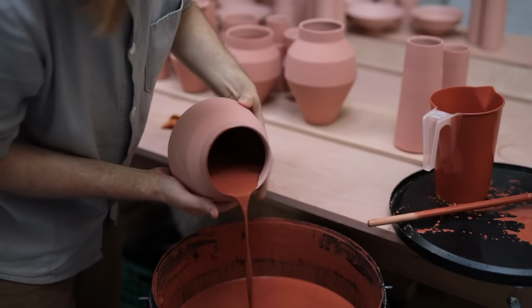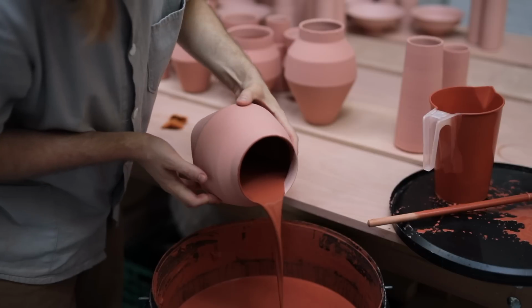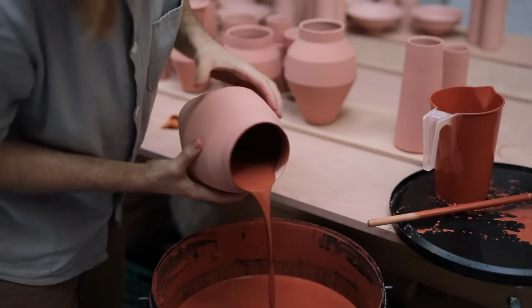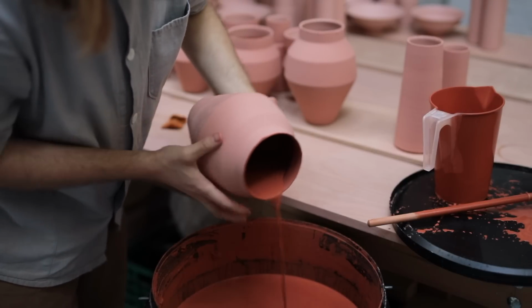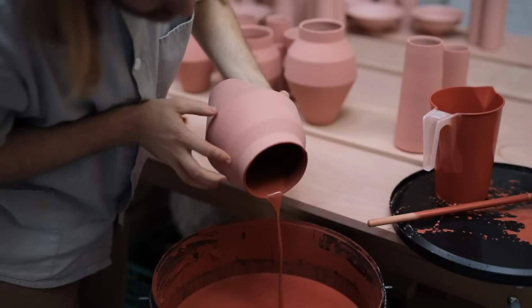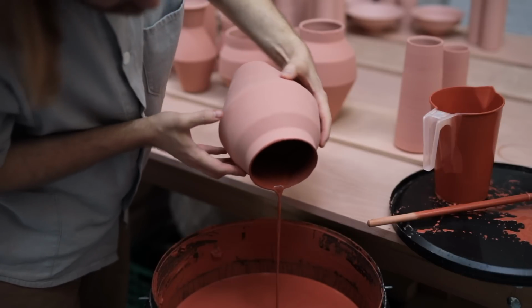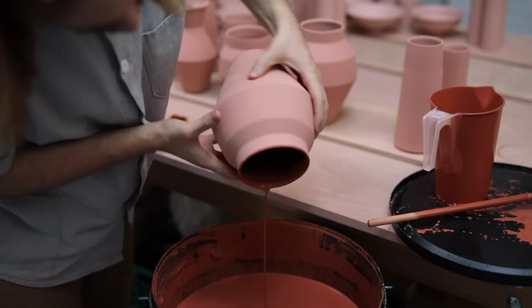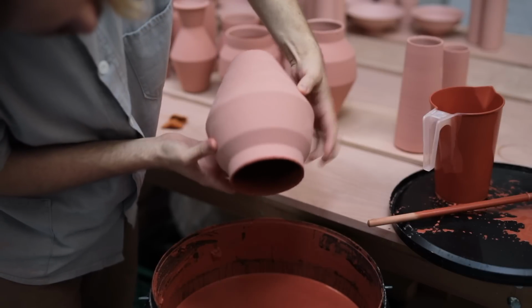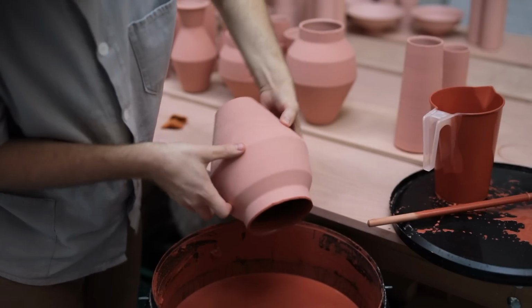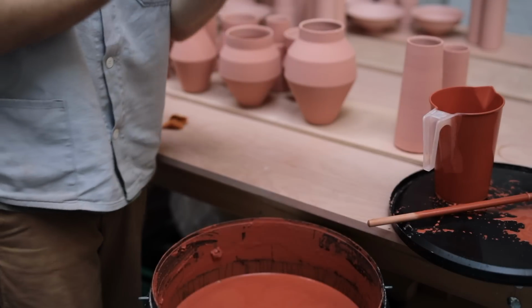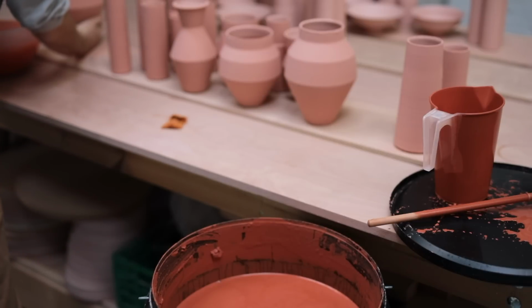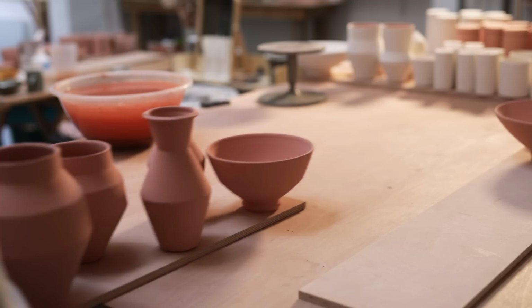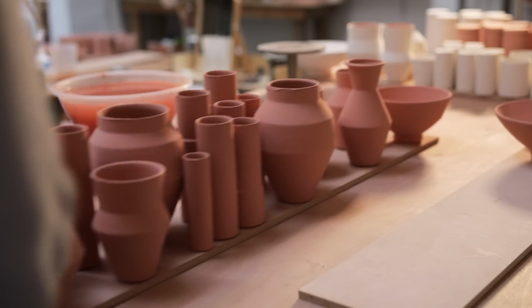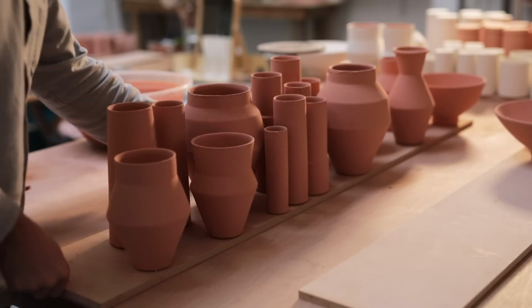And to quickly explain why I do the outside first, my glaze dries in quite a delicate layer, and if I coated the inside first and let it dry, and then gripped it from the inside to push it underneath the glaze to coat the outside, I'm pretty sure the amount of pressure I'd need to use to push the pot underneath could be enough to damage the glazed surface inside, whereas I feel it's safer to handle the outside of the glazed pot without it potentially being damaged, as I don't have to grip it nearly so hard.